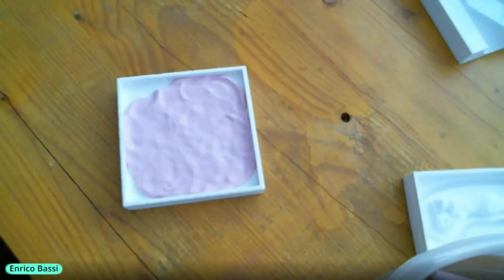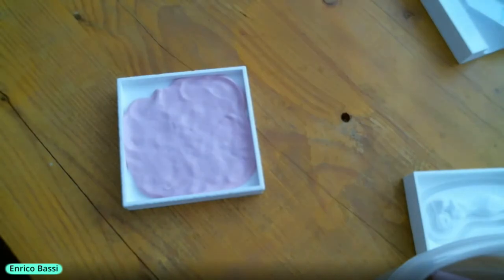No, it's important to use a specific product, as I said, because sometimes some chemicals in normal lubes could slow down or stop the curing process. So it's important to take something that is meant for that. Now, on average, you don't need that, but if you want your mold to last longer, then it makes sense to use a mold release. I want to show you how this thing looks. Let me see if I can find something to open the box.